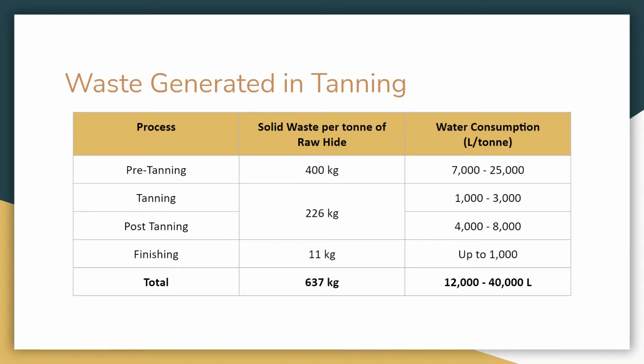This results in a typical amount of 400 kilograms of raw hide being lost in the pre-tanning stage, around 226 kilograms of raw hide being lost in the tanning and post-tanning stage, and finally 11 kilograms of leather or rawhide being lost in the finishing stage, resulting in a total amount of 637 kilograms out of 2,000 kilograms, or roughly 32% of the initial rawhide being wasted, and a typical range of water consumption being between 12,000 and 40,000 liters of water consumed for every 2,000 kilograms of rawhide.